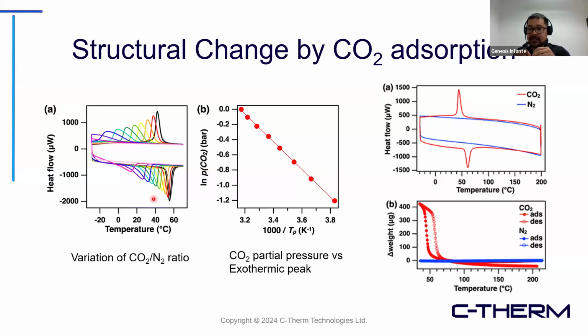And for this particular MOF, there is a known structural change as CO2 is adsorbed. As CO2 gets coordinated within the pore of the structure, that changes the pore geometry of the MOF. So you can see that with a lot of CO2, it really changed the melting and crystallization events for this particular MOF. You can also map that out with a correlation between the partial pressure and where the exothermic peak occurs, and you can see there is a linear correlation, meaning they are directly related to one another. This just shows the DSC between different gas conditions.